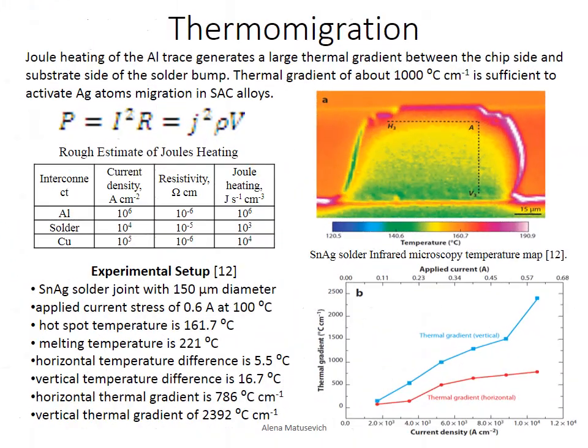Thermomigration. Joule's heating is defined as energy dissipated by a conductor per unit time, where J squared rho is the energy dissipated per unit time per unit volume of the entire conductor. A rough estimate of Joule's heating per unit volume can be calculated as shown in Table 1. Infrared microscopy was utilized to confirm the hot spot temperature profile of a eutectic tin silver solder joint with 150 micrometers diameter under applied current stress of 0.6 amperes at 100 Celsius.